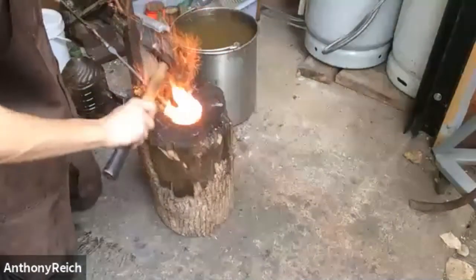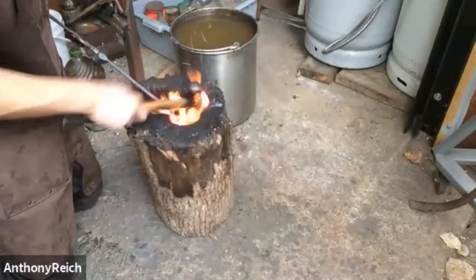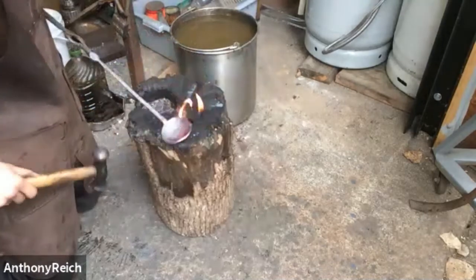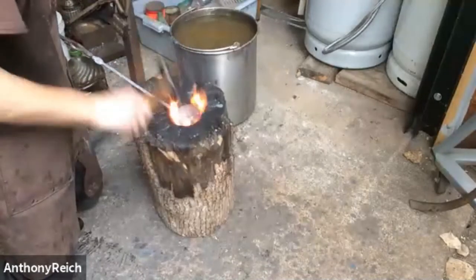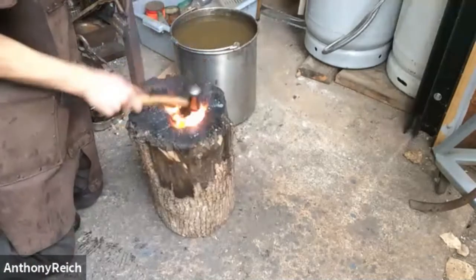You do want to make sure your material's still thick enough, especially at the dishing phase. This is where you'll realize it's too thin, because it'll crinkle up like paper and either crumble away or break, or you'll just have a hole in it.